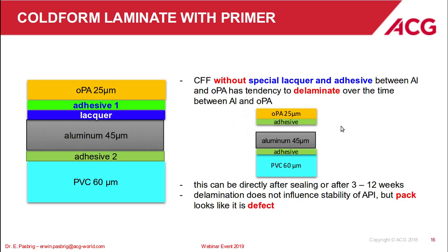Here you see both structures. On the left-hand side is the material with the primer. Primer is a thin layer of lacquer. Because it's thin, it's called primer. The reason for the primer is that oil, still on the soft tempered aluminium surface, hinders the bonding strength with the adhesive on the outer side, and over time the laminate lifts up from the aluminium, which is one reason of delamination. The adhesive on the outer side is not identical with the adhesive for the material without primer. It's a different one. Lacquer and adhesive have to work together.